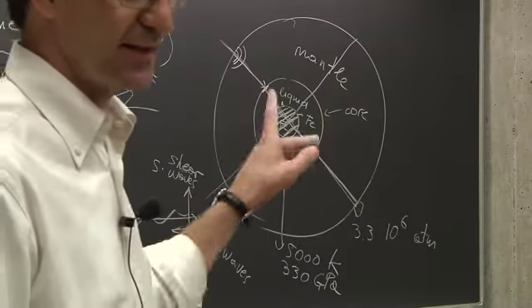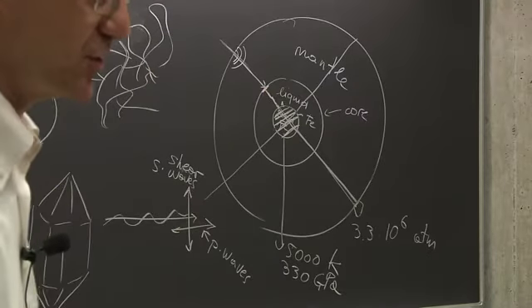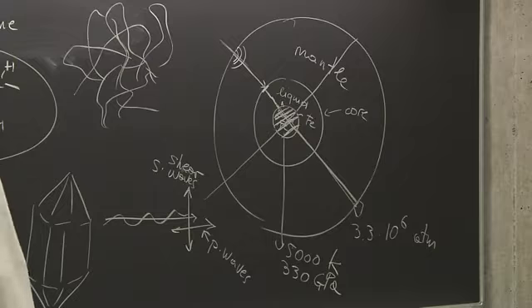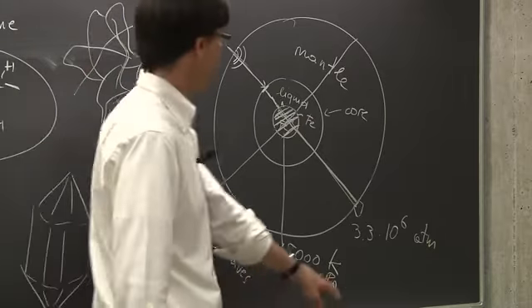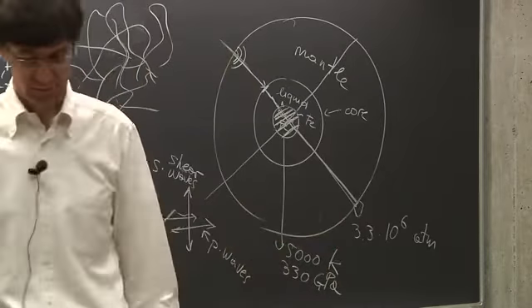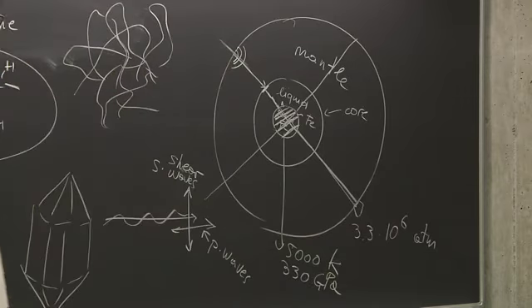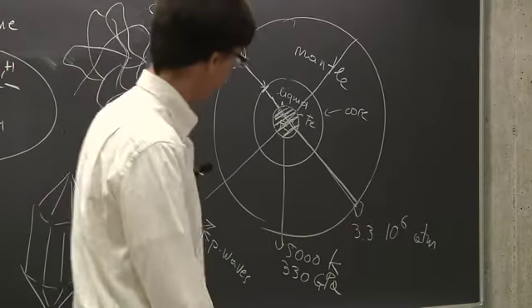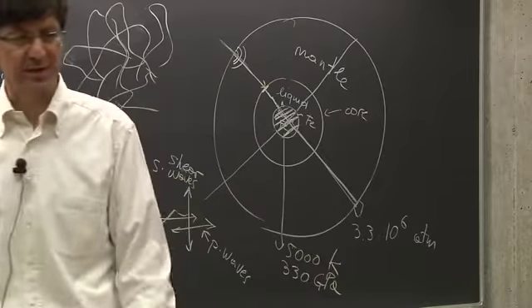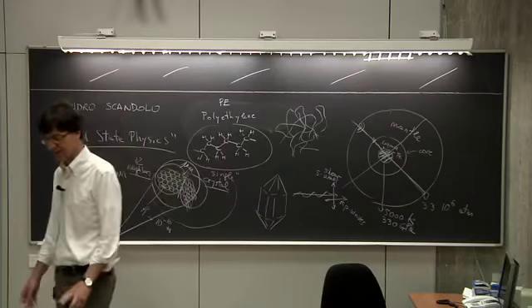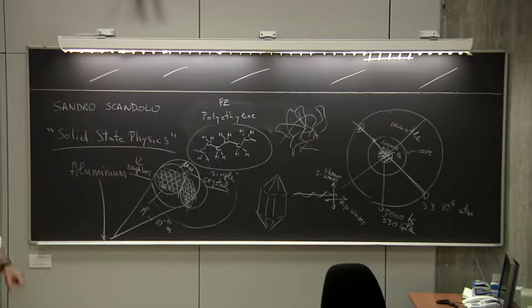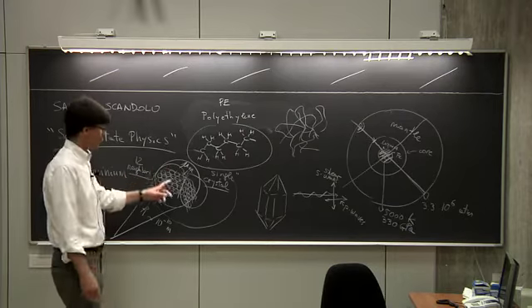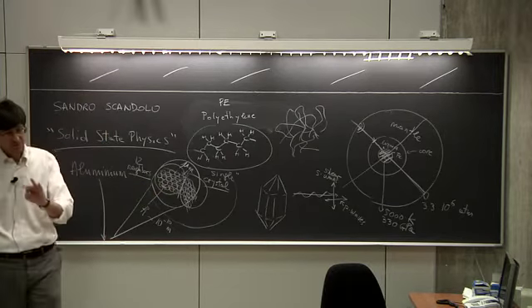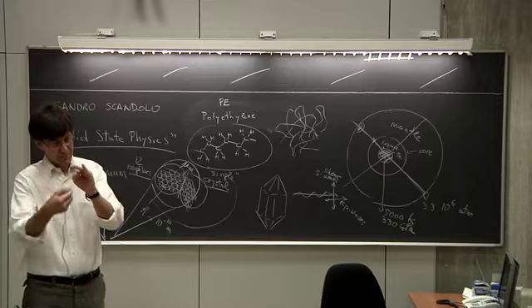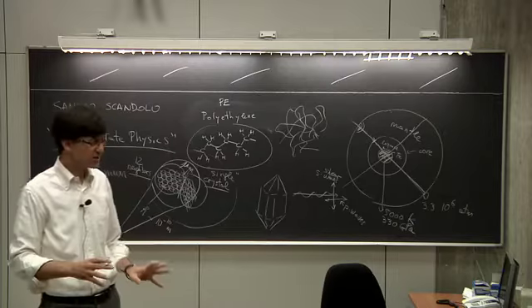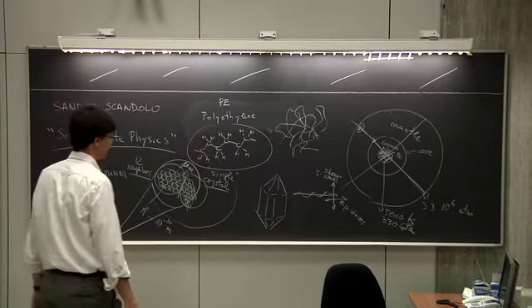No experiment yet has ever been able to get to those pressures. We are close. There are experiments currently being done in France. They are getting to about 1 million atmospheres. So it's only a factor of 3 off. And I guess in the next few years they might be able to get there experimentally and try to measure the sound waves. Of course, then you must be able to grow a small single crystal in your lab and then do the experiment with sound waves in different directions. It's a challenge, but it's not impossible, of course.